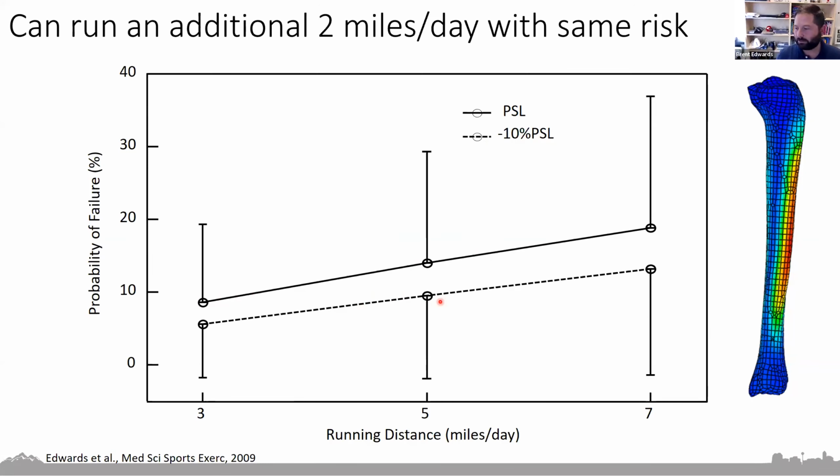So you decrease your stride length, the strains go down for a given step, right? But at the time people had a question: if you decrease your stride length, you increase the number of loading cycles, which might be detrimental. Well, this model would seem to suggest that the benefits of decreasing the strain magnitude outweigh the detriments of increasing the number of cycles for a given running mileage.